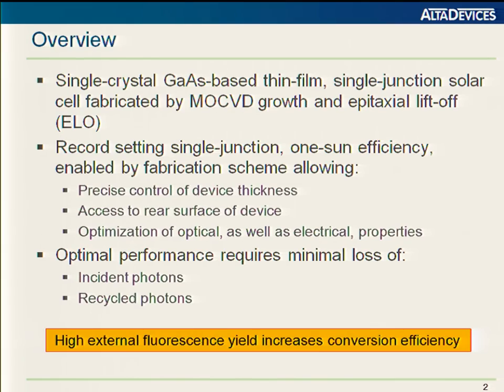So again, I'm going to be talking about a single crystal, single junction gallium arsenide device in a thin film, where the thin film is made by metal organic chemical vapor deposition, and then the film is lifted off, leaving a reusable wafer underneath it, and the film thickness is then controlled by the MOCVD growth. With this approach, we've managed to achieve record efficiency by the fact that we can access the backside of the device and precisely control the device thickness.